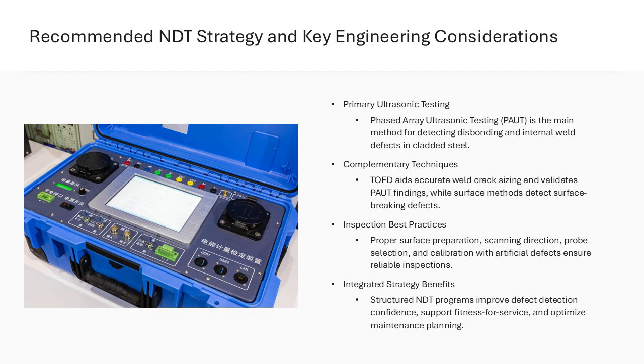TOFD should be used as a complementary technique for accurate weld crack sizing and validation of PAUT results. Surface inspection methods such as liquid penetrant testing and eddy current testing play a crucial supporting role in identifying surface-breaking and near-surface defects. Key considerations include proper surface preparation, inspection from the carbon steel side where feasible, and the use of representative calibration blocks with artificial defects to validate procedures. Scanning direction, probe selection, and data interpretation must be carefully controlled to ensure reliability.